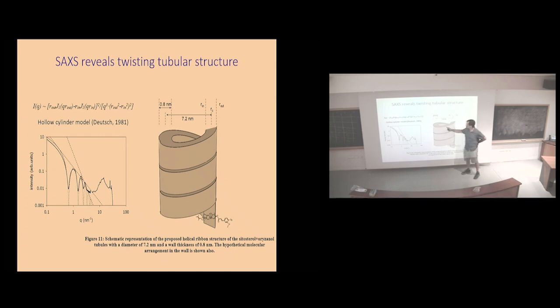A hollow cylinder of about 72 angstroms in diameter. And he had to consider the internal radii, the outside radii, the size of the wall. All of those things belong in the model that you have in there. Very interesting structure, really nanoscale at 7.2 nanometers. These things are really nanoscale structures. And some people were excited because maybe you can put things inside.